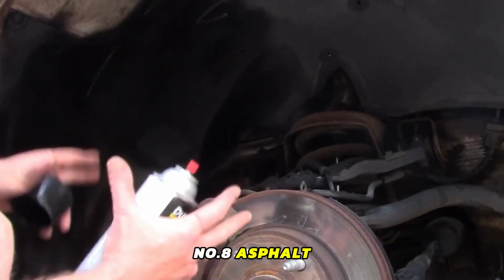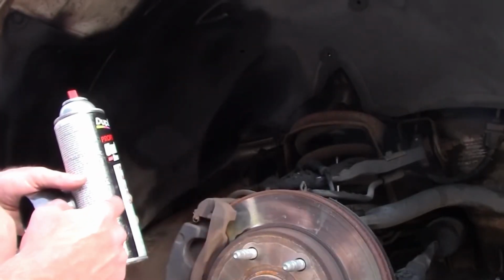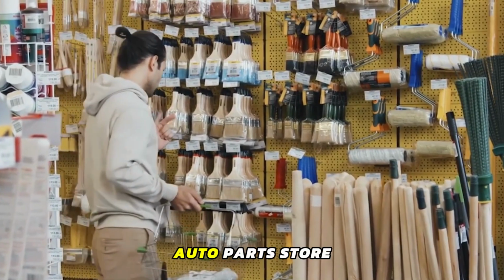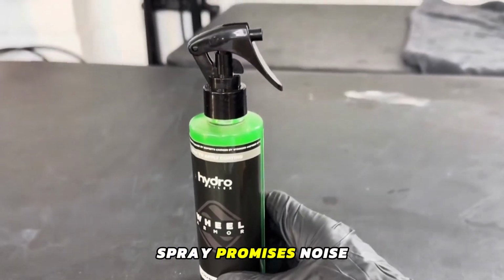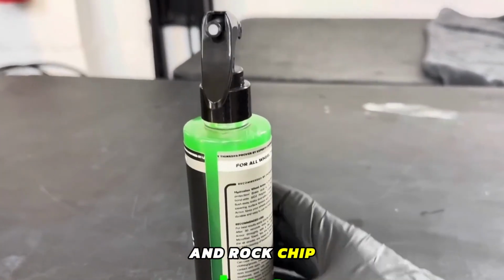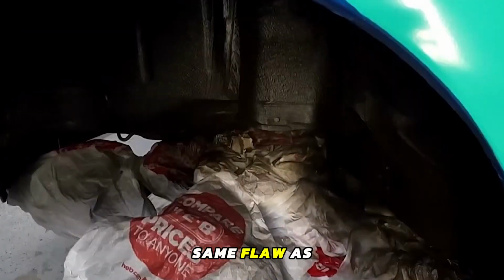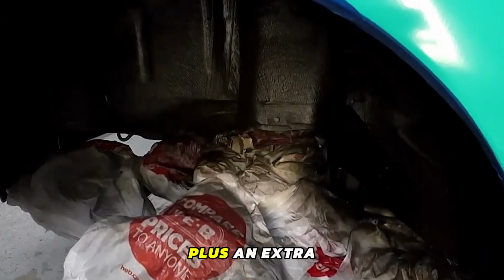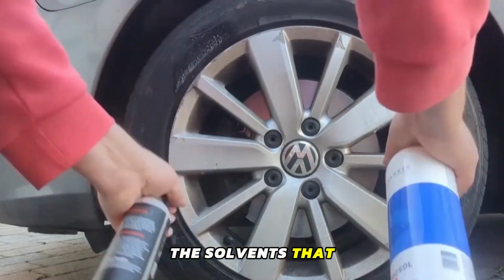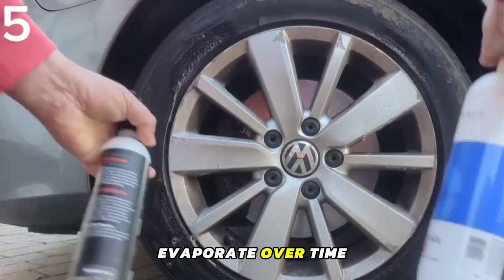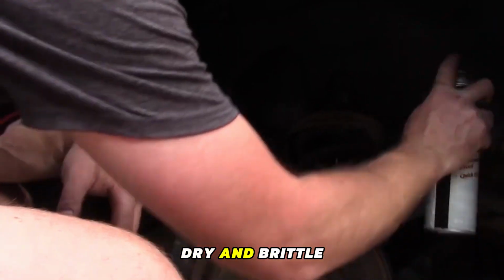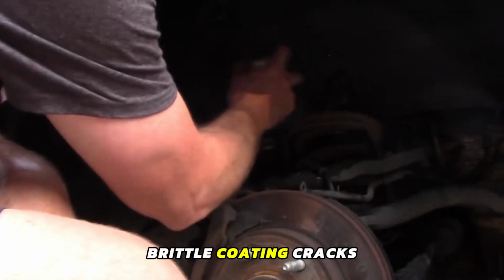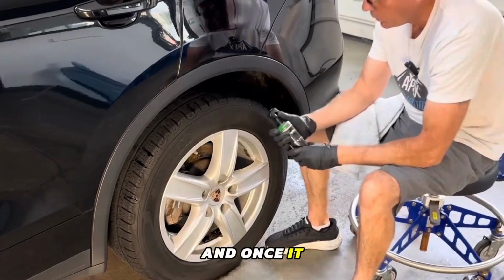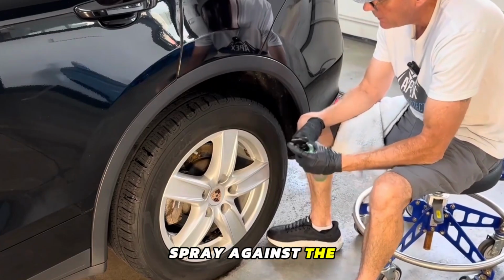Number 8. Asphalt-Based Wheel Well Coating. Sold in tall cans at the auto parts store, this tar-like spray promises noise deadening and rock chip protection. It shares the same flaw as rubberized undercoating, plus an extra one. The solvents that keep it pliable in the can evaporate over time, leaving the coating dry and brittle within a year. Brittle coating cracks with road vibration, and once it cracks, it traps salt spray against the wheel well